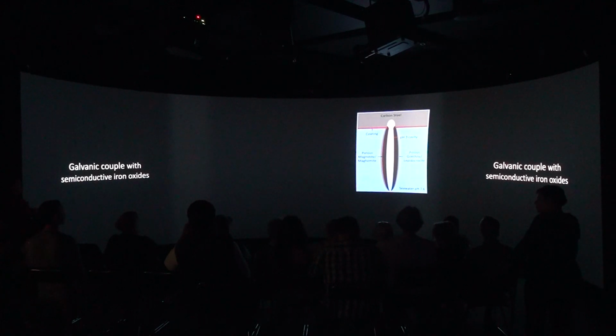There have been reports of rusticles having pH 3 inside the cavities. So the inner layer of iron oxides is magnetite or maghemite, which are semiconductive, and they are forming a galvanic couple with the steel of the shipwreck. And once they come in contact with the seawater, they start dissolving the iron in this little cavity. And once this iron starts leaching out of the cavity, it comes in contact with the seawater and the small amount of oxygen that it has, and precipitates.